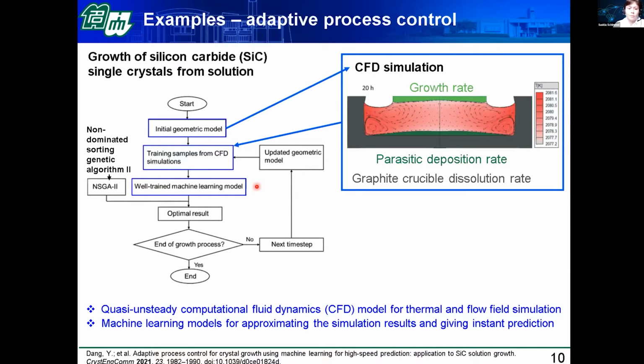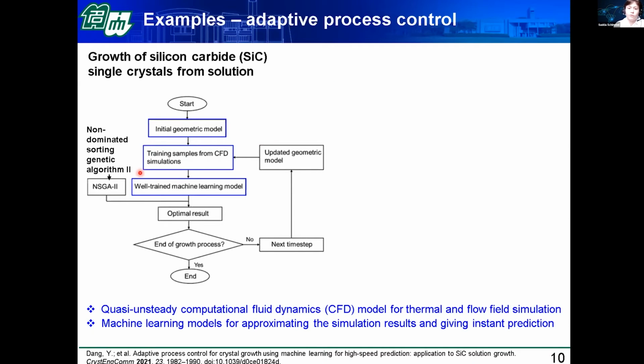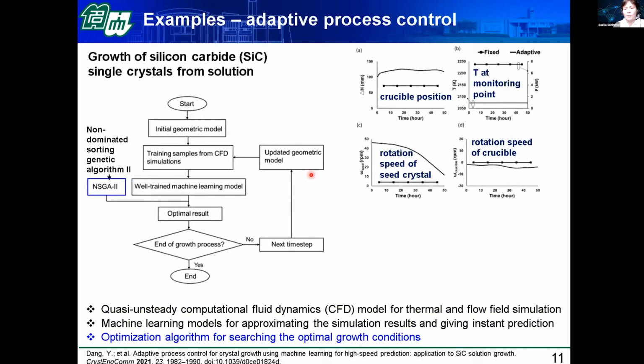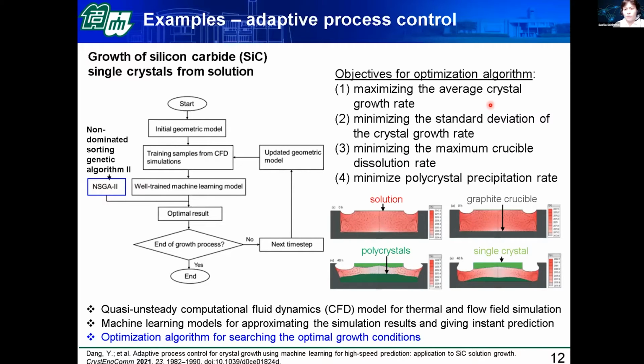And then a second component of this work comes into play, which is an optimization algorithm that was used for optimizing controllable parameters such as the rotation speed of the crucible and crystal, or the position and the temperature. And the objectives were to maximize the growth rate, to reduce the standard deviation of the growth rate, and to minimize both the crucible dissolution rate and the polycrystal deposition rate. And they could show that in all those fields, significant improvements were made by this adaptive process control.